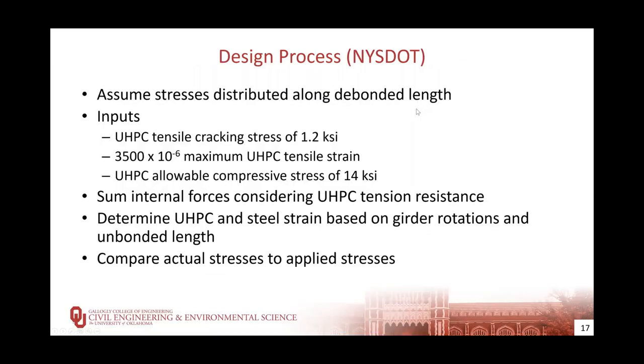We're talking more about service life in this project, but in general, the design of a link slab is such that we assume the stress caused in the link slab is distributed along the debonded length. We're going to use a tensile cracking stress based on the strength of the material. New York DOT uses 1.2 KSI and a maximum tension strain of 3,500 microstrain. The UHPC has an allowable compressive stress of 14 KSI in their design procedure. We then sum the internal forces, considering UHPC providing tension resistance, determine the UHPC and steel strains based on the girder rotations and the unbonded length, and then compare the actual stresses to the applied stresses and work those out to get to where we're below the allowable stresses in the link slab.